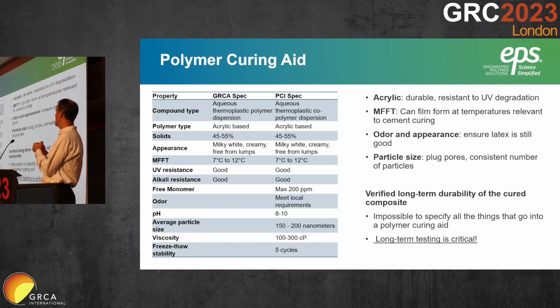Acrylic or acrylic copolymer based means that it's made up of acrylate monomers. Acrylic is a polymer that's known to be resistant to UV light and resistant to hydrolysis, so when it's in the water in that alkaline environment, it won't degrade. Solids, 45 to 55%. The higher the solids, the more polymer you're getting instead of water or something else. Appearance, milky white, creamy, free from lumps. It's a quality assurance thing. If it's lumpy, then there's probably something you should call your supplier and talk to them about. UV alkaline resistance, good. We talked about MFFT already. Free monomer: that's basically the amount of residual chemicals in there, and lower is better.